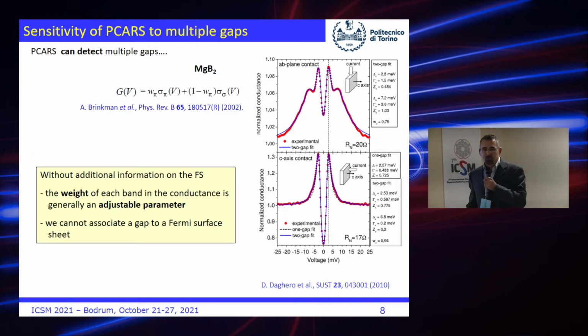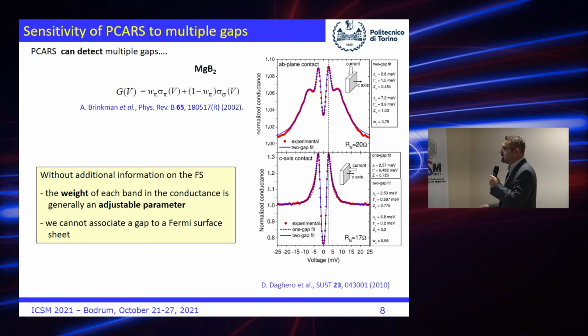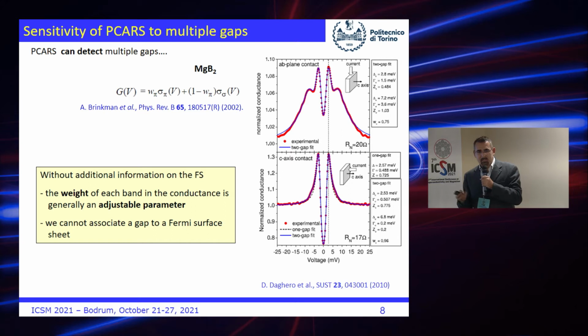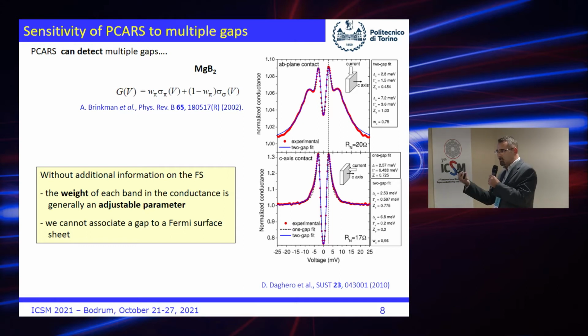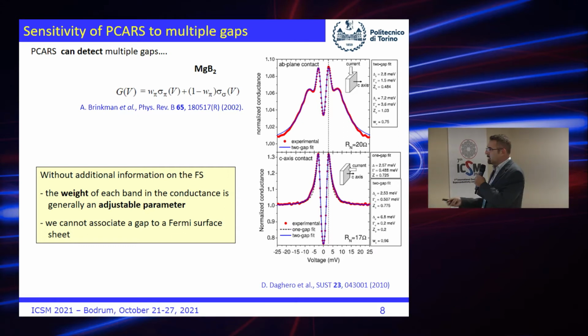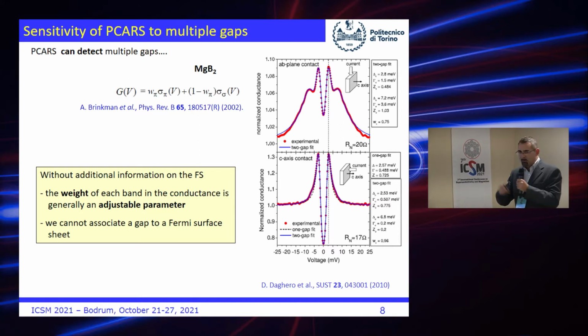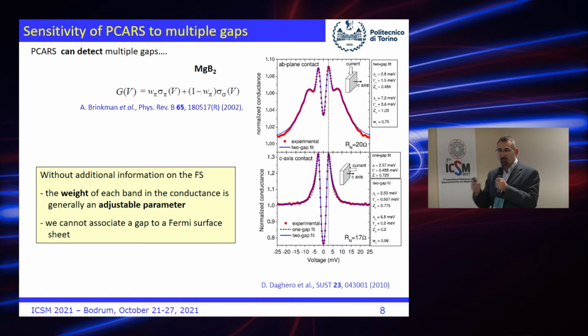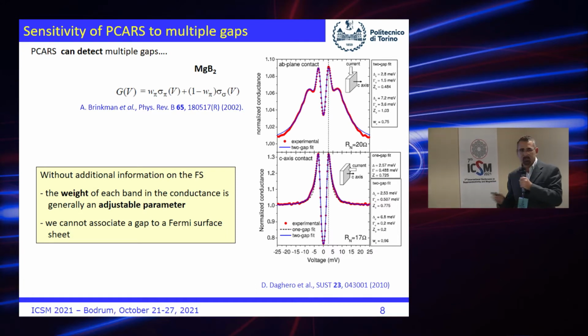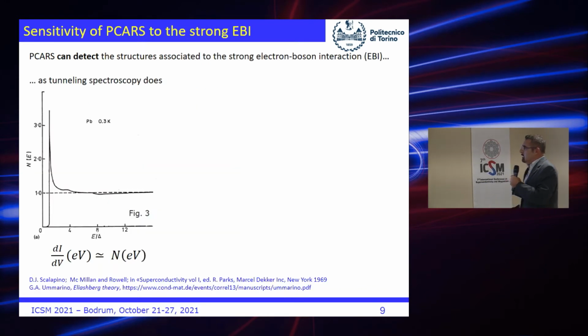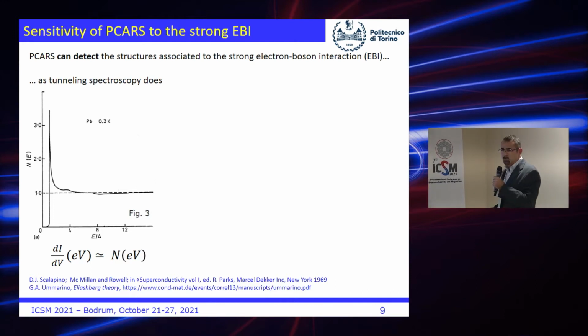Now, in the case of multiple gaps, which is the case of iron-based superconductors, there is nothing special actually. As in the case of MgB2, it was shown that the total conductance can be calculated within the model by calculating first the partial conductances associated to the different bands that host the different gaps, and then summing them by using a suitable weight. This weight actually depends on the shape of the Fermi surface and on the direction of current injection, but in the absence of clear information on either of these two quantities, it is just an adjustable parameter of the model.